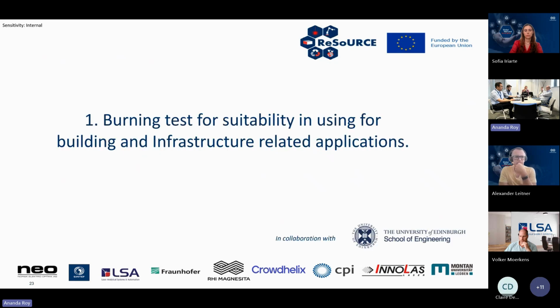Starting initially with the burning test of these materials, which we used within a standard epoxy. As global fire regulations continue to tighten up, there's a growing demand for these non-halogenated or low toxicity flame retardants. Refractory materials, as a matter of fact, can withstand extremely high temperatures, and it shows those characteristics of making them potential candidates as functional fillers within fire-safe polymer composites. So in this case, we'll try to evaluate the fire performance of the epoxy composites, incorporating these two refractory waste-derived fillers, M-Ferro and M-Chem, and compare their effectiveness with that of a conventional flame retardant benchmark, aluminum trihydrate.